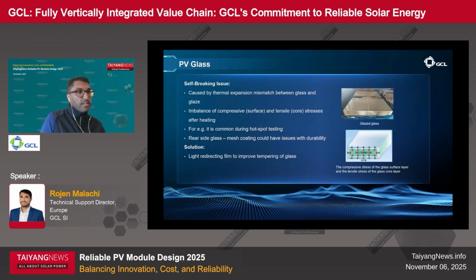Back glass durability has been a major industry topic, and we've heard of some manufacturers with modules that have lots of issues on the rear side of the glass. This could be because of the mesh coating that's used. To overcome this, GCL uses a redirecting film to improve the tempering of the glass. This minimizes spontaneous glass fracture risk, and this, at the end of the day, has a lot to do with the thickness of the glass and how the thickness has been reducing over the last years. So reliability is not just electrical, but also on the mechanical side.